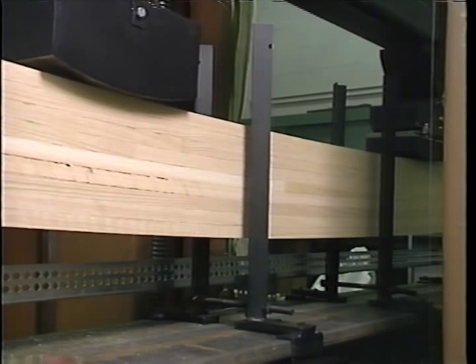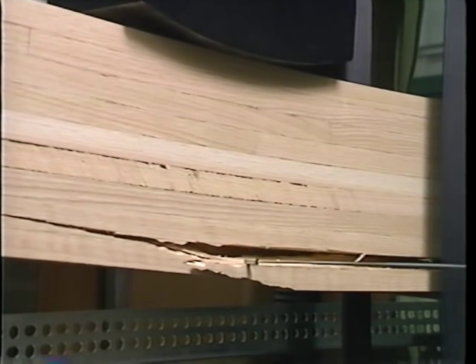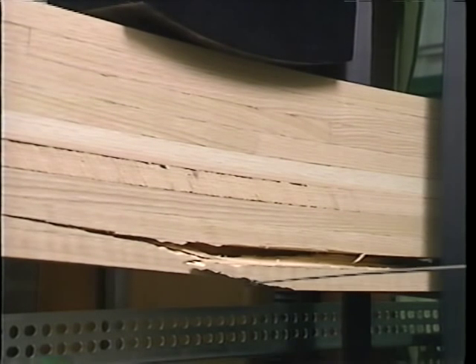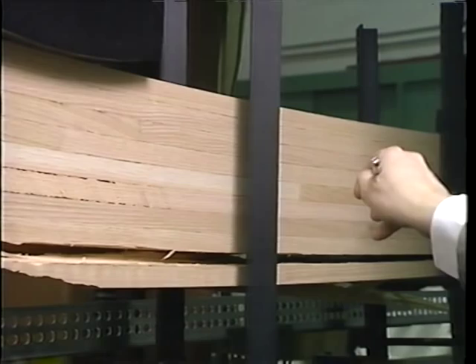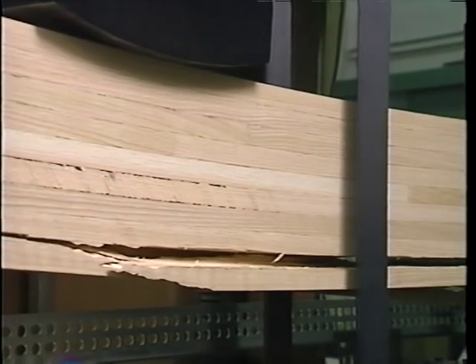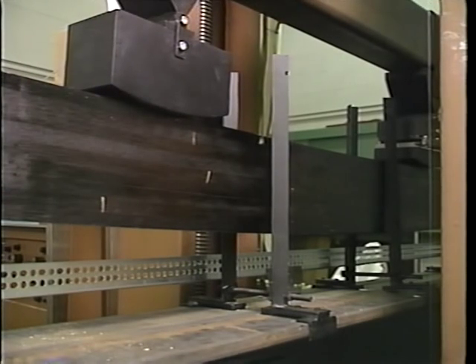The Penn State research team conducted testing in accordance with the American Society of Testing Materials. The goal was to determine the strength of the red oak glue lam beam and to compare results for untreated versus preservative treated beams. The failure occurred in the wood rather than in the glue line, and that is important and critical. Over 100 beams were successfully broken by the Penn State research team, confirming that treated and untreated glue laminated northern red oak is a viable construction material.